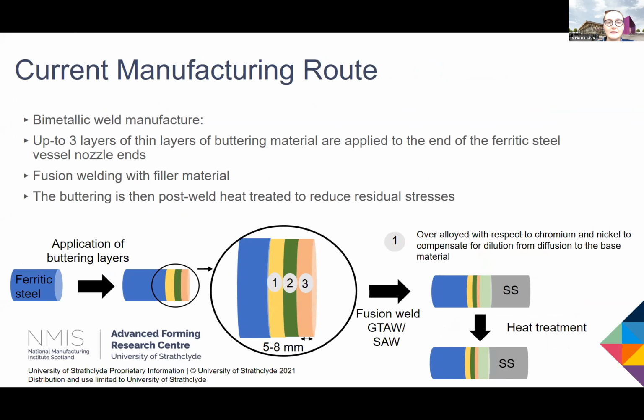In terms of the current manufacturing route for these bimetallic joints, if you look at the very simple schematic at the bottom, we have ferritic steel, and you can have up to 1 or 3 layers of a thin buttering material applied to the end of the vessel nozzle. Those layers are normally about 5 to 8 millimeters in thickness, and the first layer is often over-alloyed with respect to chromium and nickel, and that's to compensate for any dilution from diffusion through to the base material. There's also a filler material usually required, and then after all the buttering and filler material, which are normally added via submerged arc welding, there's often residual stresses generated within the joint, so a post-weld heat treatment is often required.